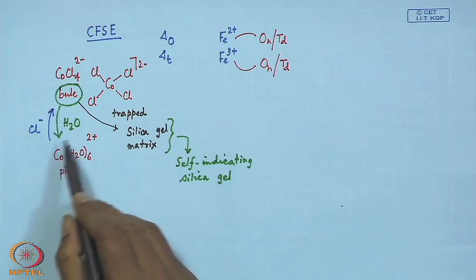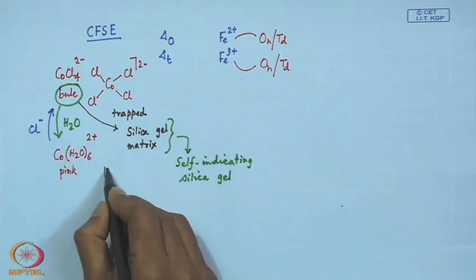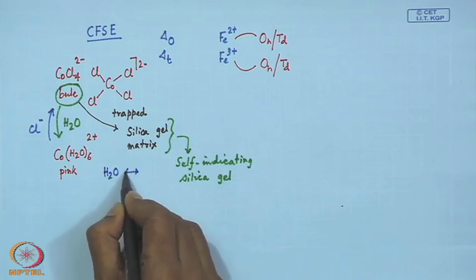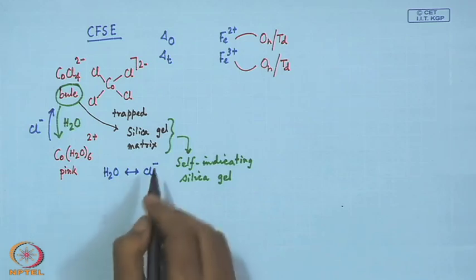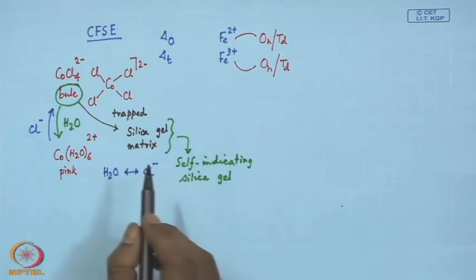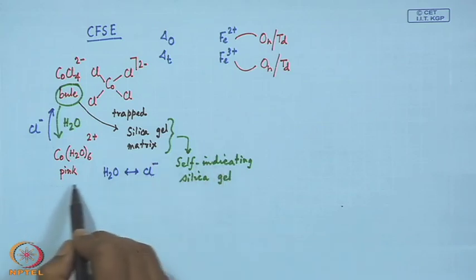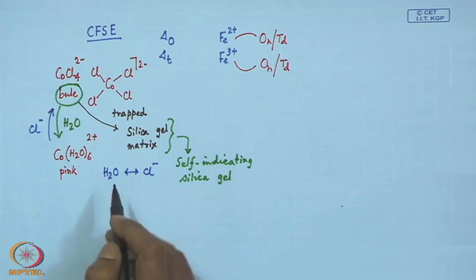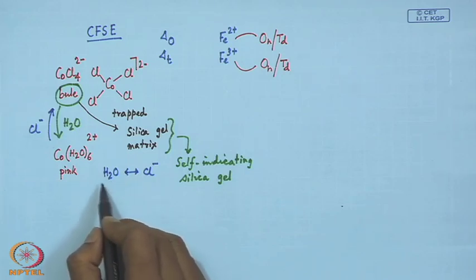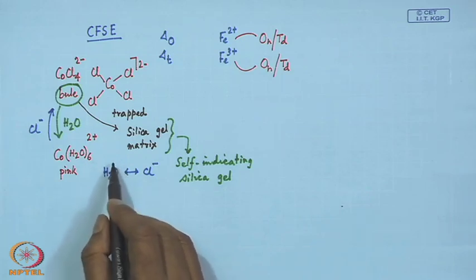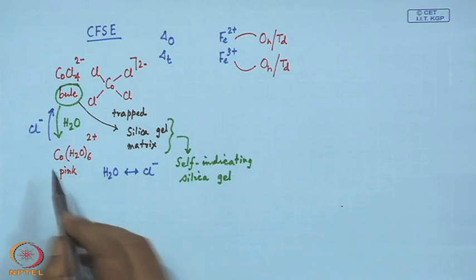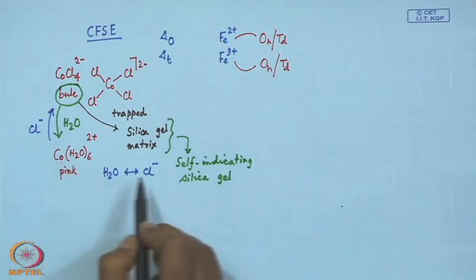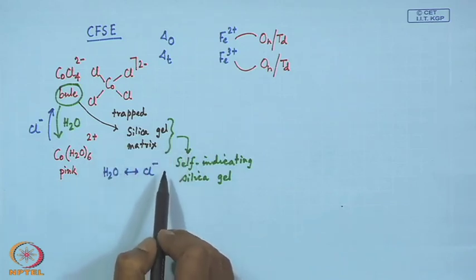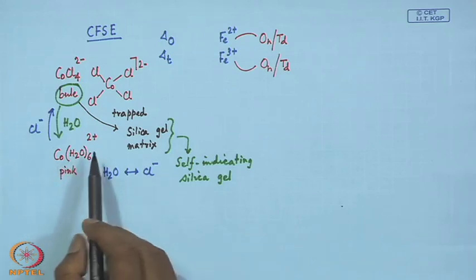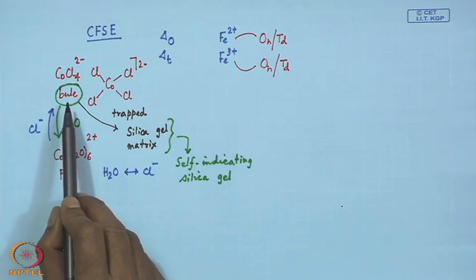It cannot leave the corresponding silica gel matrix, but it will have only competition with the water molecule with respect to Cl minus. So Cl minus will be still there, but it is not coordinated to the cobalt center. When we put this pink colored silica gel in an air oven at around 100 or 120 degrees centigrade, we see that when we remove these moistures at this particular temperature, these water molecules will go out from the cobalt site, and these Cl minus anions which are nearby trapped within the silica gel will approach again back to the cobalt site, giving the silica gel again the corresponding blue coloration.